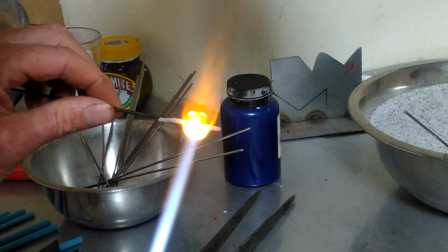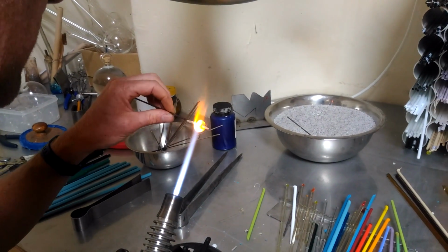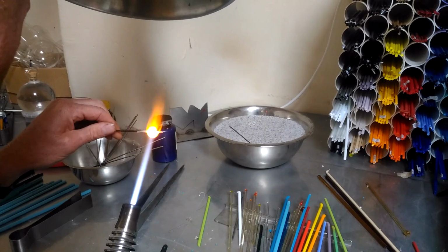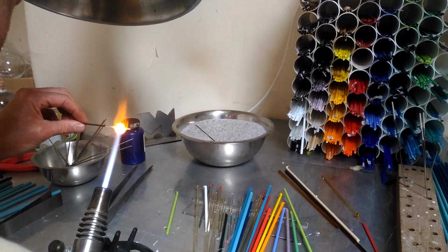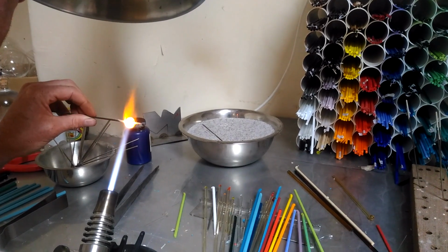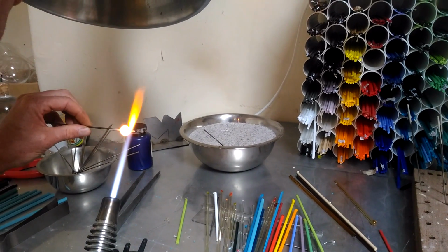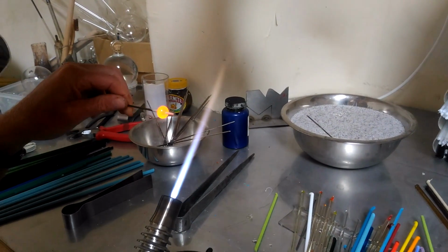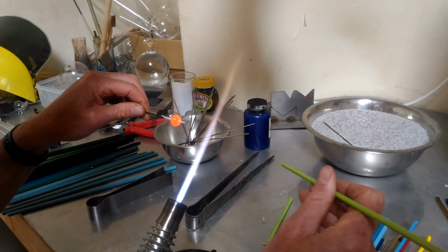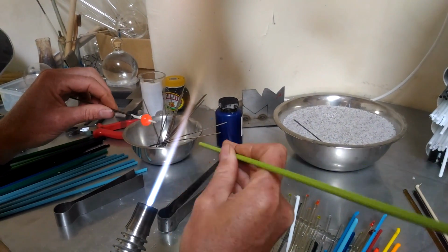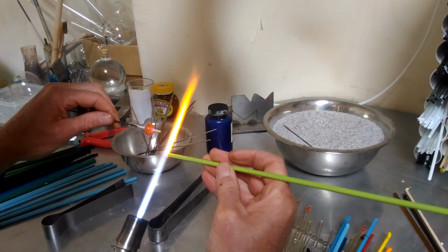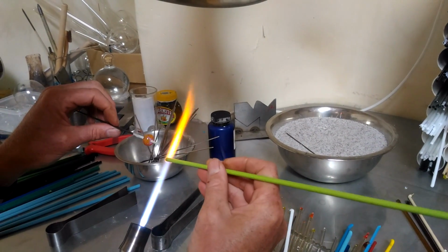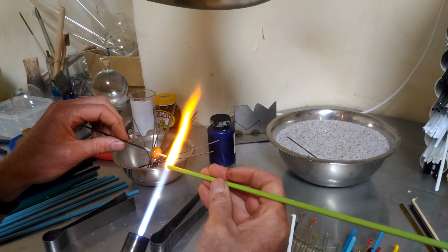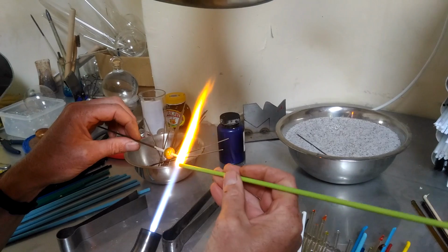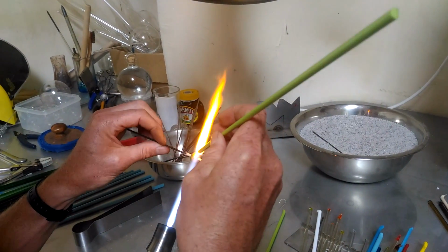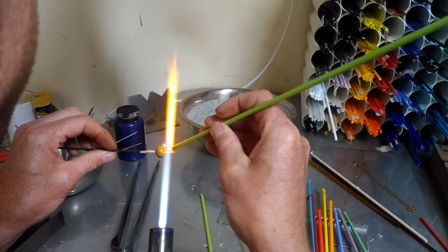But the flame on these nice quiet and very, very hot torches comes from a mixture of two gases, oxygen and propane. It's a much nicer, hotter flame. You can make beads in just single gas torches, like propane torches, but they're very noisy, and also the flame's not hot enough, so you don't have the control. But with these, you can actually change the chemical composition of the flame. If you add more oxygen, you get an oxidizing flame, which will add oxygen to the colored glass and change the color of the glass itself. It creates a chemical process.